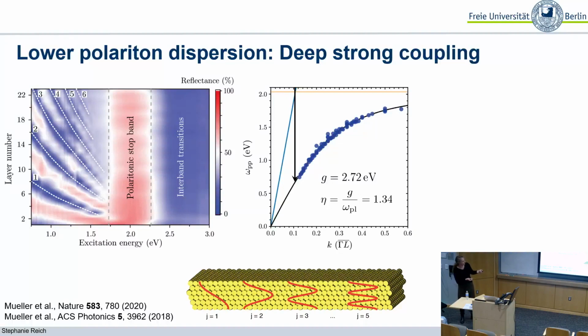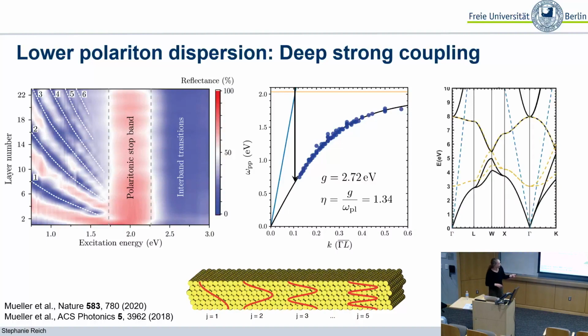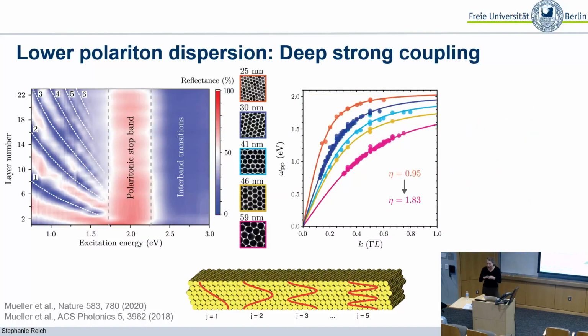And from that, we got these data points here. If you remember the calculations we had before, what we are looking at is this transverse plasmon polariton branch down here, and we can fit it to a Hopfield-like expression of a polariton, and from that extract the light-matter interaction strength, almost 3 eV, and the ratio between the light-matter coupling and the original frequency. We were very proud to see that we are indeed in this regime of deep, strong light-matter coupling. And we did that for many different sizes of gold nanoparticles and different distances. So we varied the packing density, and thereby you can tune the reduced light-matter interaction from roughly 1 to almost 2.